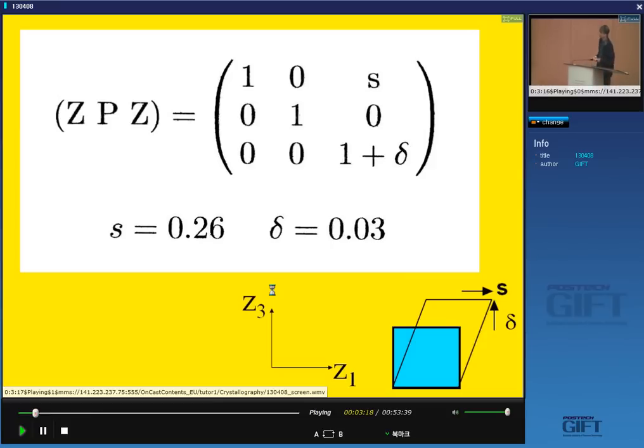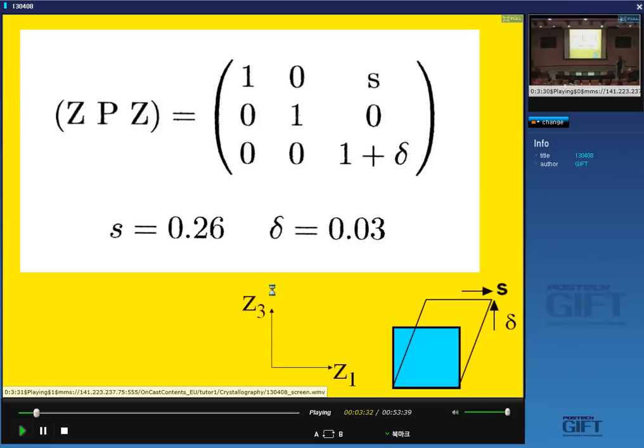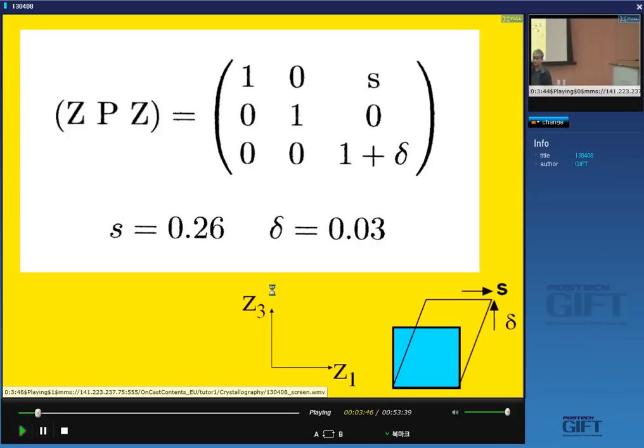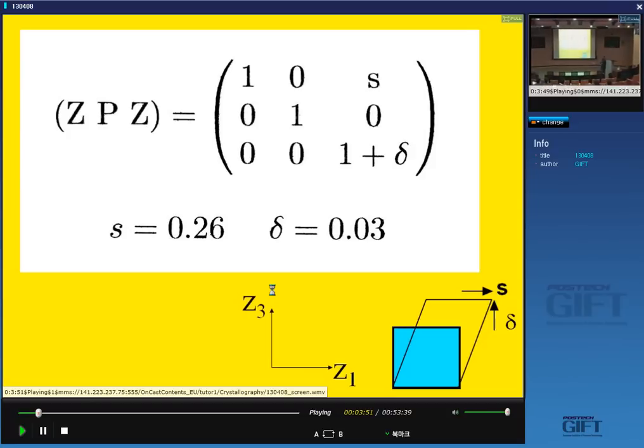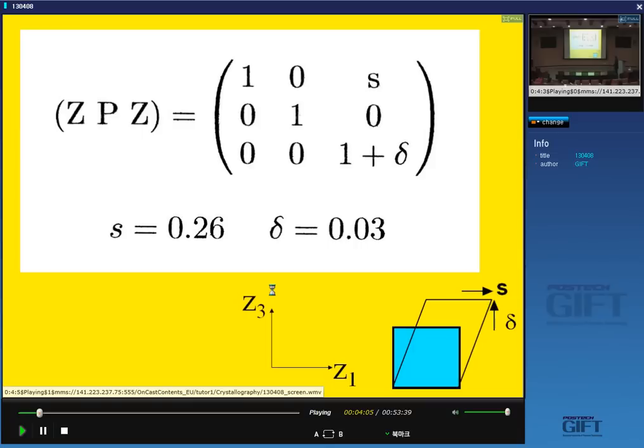Just to revise what we've done in a previous lecture: the transformation causes a deformation properly described as an invariant plane strain — it leaves one plane unrotated and undistorted. For steels, the shear strain is of the order of 0.26, and the volume change normal to the habit plane is approximately 3%, or 0.03. By choosing a coordinate system Z where Z1 and Z2 are on the invariant plane and Z3 is the normal, we can easily define our deformation matrix. The vector (1,0,0) and (0,1,0) undergo no change, while the vector along Z3 acquires a component along the x-axis, giving us our deformation matrix.